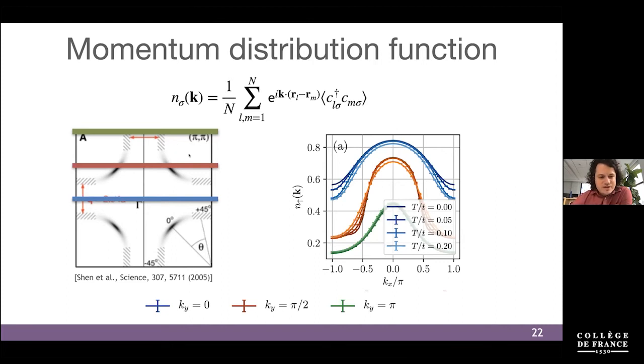What I'm showing here is a cut through three lines of the Brillouin zone. We are simulating this on a width 4 cylinder, which has a resolution of 4 discrete momenta in the y direction, and these are shown in different colors. Whenever we are at ky equals pi, we plot green, which is this line here. Whenever we are at ky equals pi over 2, we plot it in red, and ky equals 0 in blue. What we are looking for, if there were a Fermi surface, would be a discontinuity at T equals 0. However, we do not really observe this.